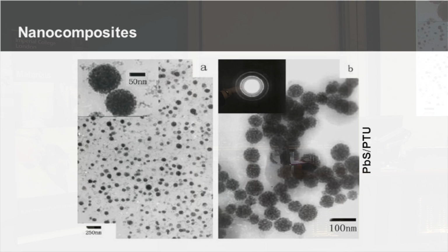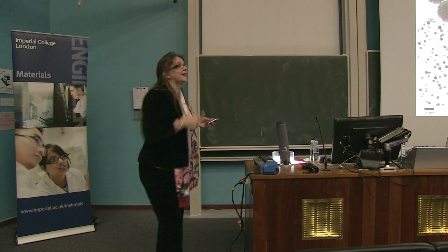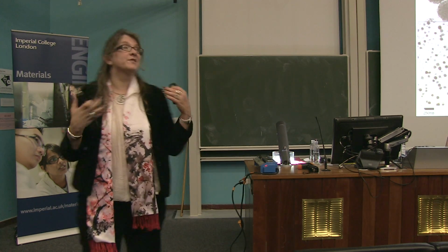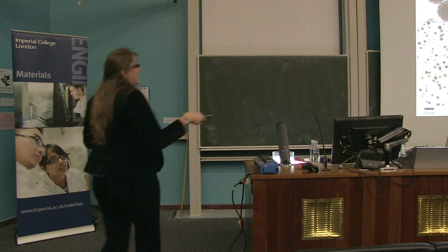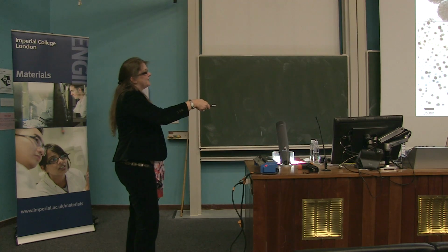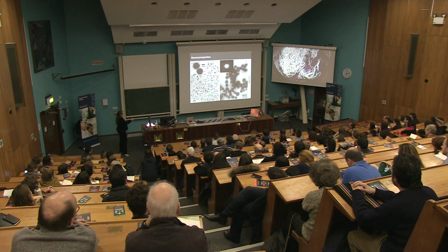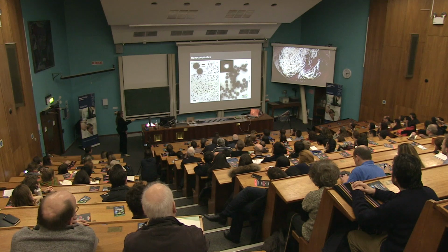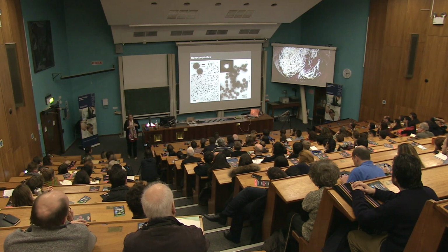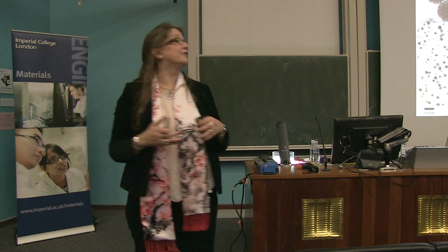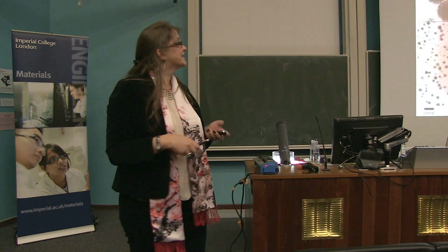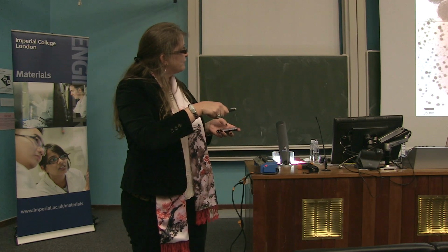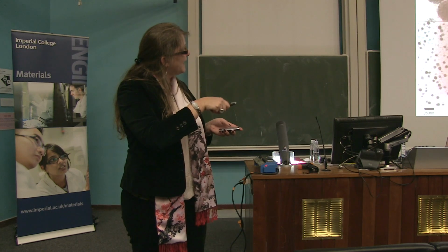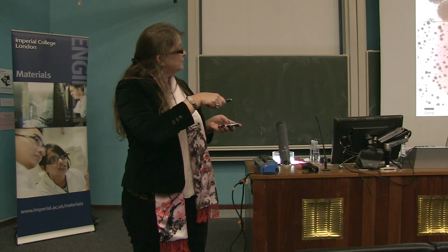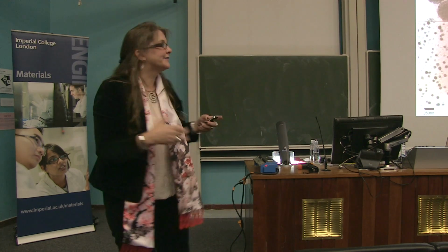The light part is the polymer matrix, it's polyurethane, like you have in mattresses or so. But you see these particles are in the range often of a few tens of nanometers to 100 nanometers. So we get sort of to the wavelengths of light. And that's why they scatter. So it's not the best picture; afterwards, you will show it. It's films of these nanocomposites. And you see they're whitish because they scatter light.